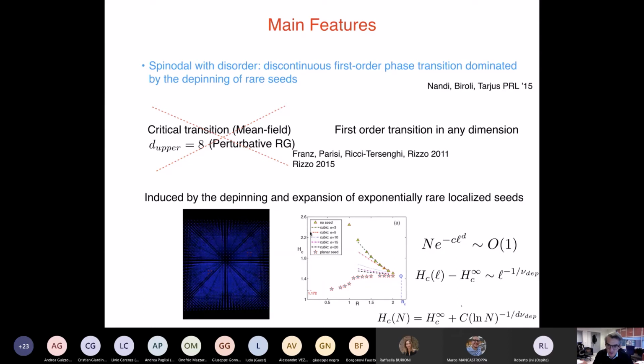The other interesting thing that you find in this curve is that you can really see the existence of the critical point. So we know that if R, the strength of the disorder, is small enough, then the hysteresis is discontinuous. But then at a certain point it becomes smooth. If R increases, it has a smooth behavior, and it goes to a critical point. And you can really see it here, because the effect of the seed disappears at the value of R which really coincides with the value of RC that we know for the random field Ising model.